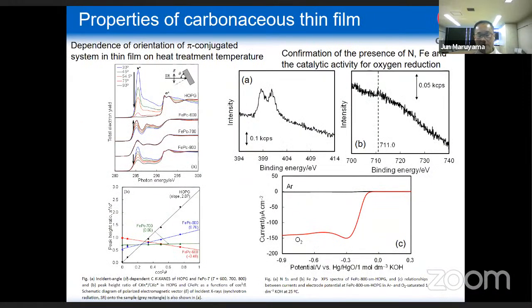And X-ray absorption spectra also show us information about the orientation of the layer, if it is perpendicular to the surface or horizontal to the surface. Actually, this is horizontal, and we can also get some catalytic activities on the surface, and the presence of nitrogen and iron was also observed.